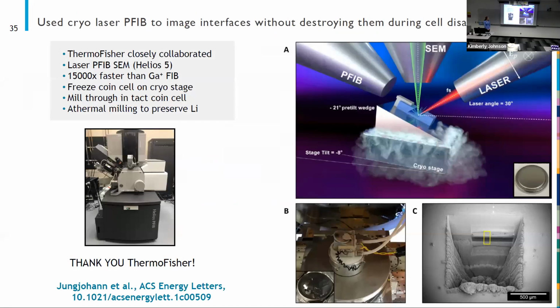So my colleague, Katie Jungjohann, had learned of this new instrument that Thermo Fisher was making called Helios 5. And normally you have a gallium ion beam that comes in and mills through your sample. And this instrument was different in that it had a femtosecond laser, and that could athermally mill through material about 15,000 times faster than gallium FIB. So this is kind of a game changer for what we're able to do.